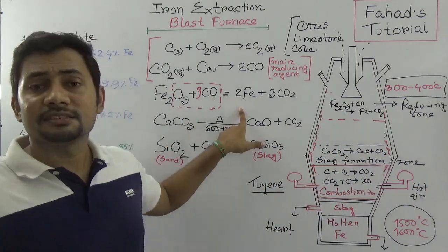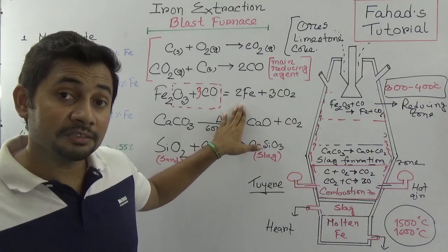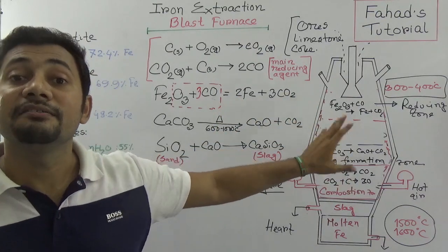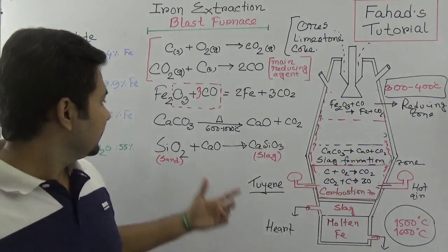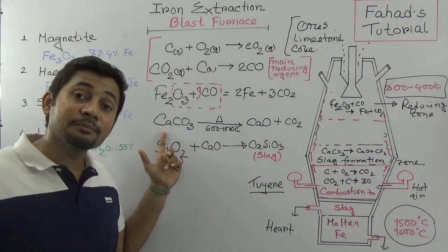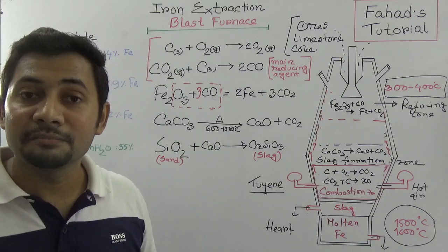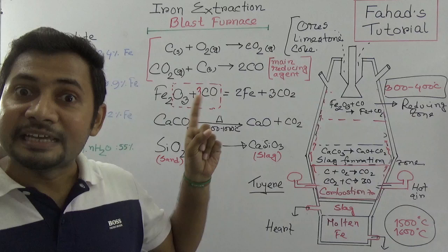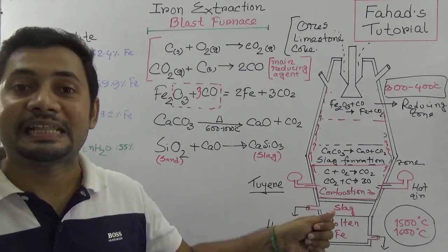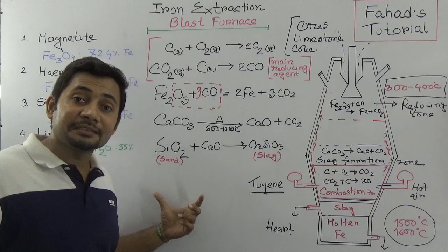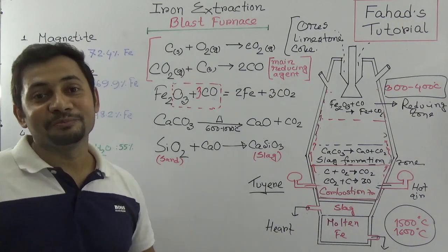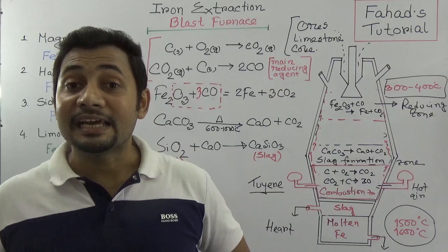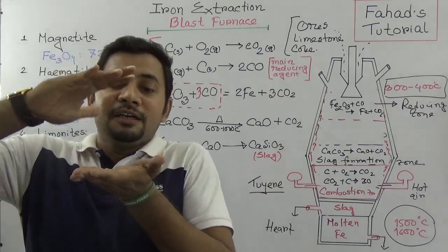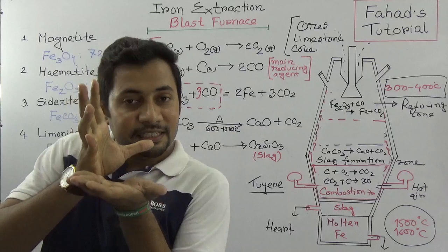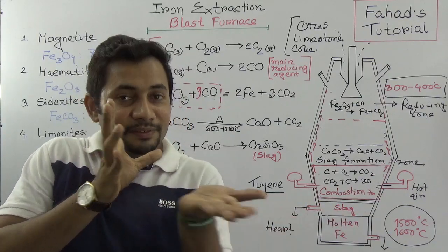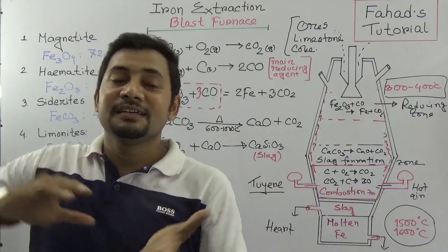So we can say this is a carbon reduction process, and these things are happening in the reduction zone or reducing zone. In other case, the limestone, which is still mixed up with ores, would be thermally decomposed and produce calcium oxide. That is the main agent to produce slag. So the sand which is mixed up with this iron oxide would be slag, and that slag would be collected from the upper part of the molten iron. So iron is collected at the bottom of the blast furnace, and then from upward slag is being collected.